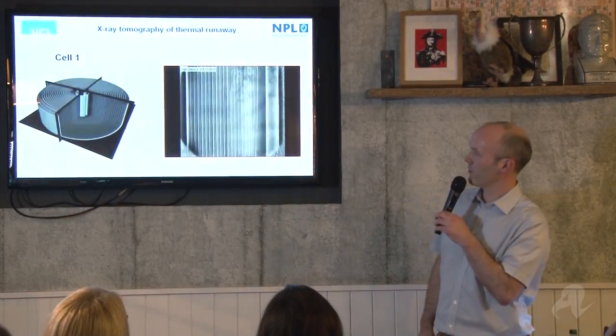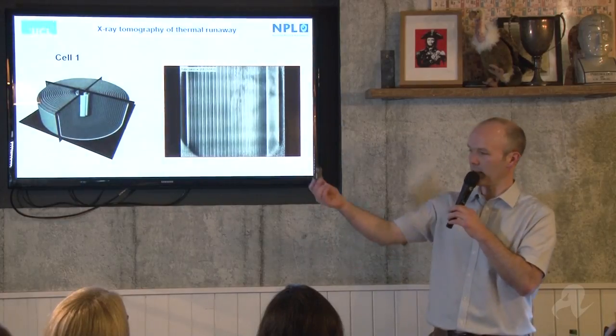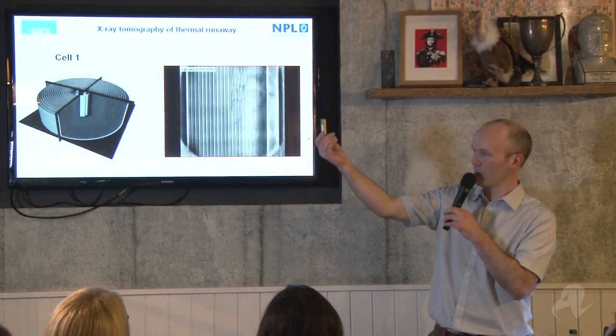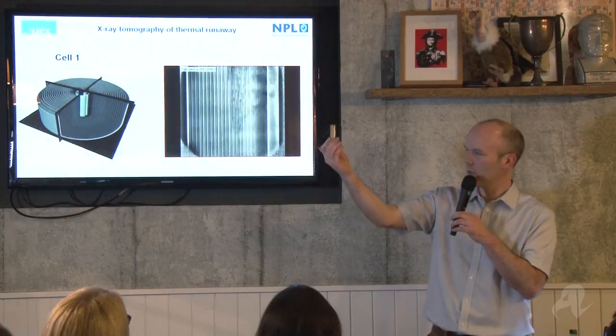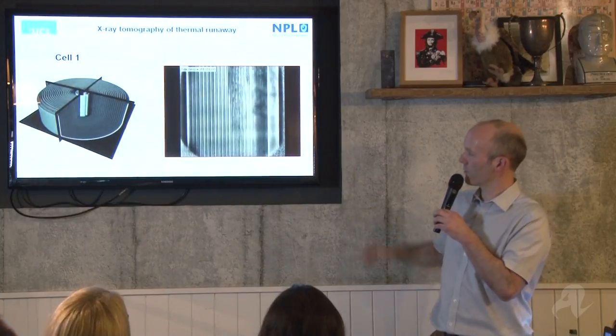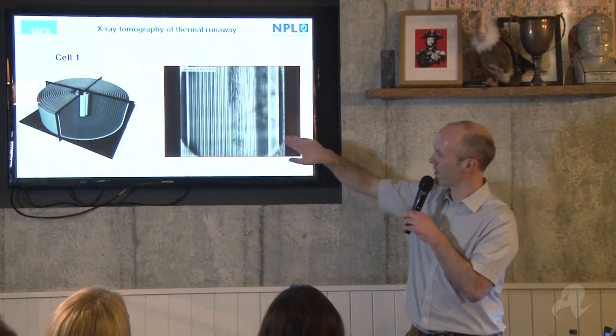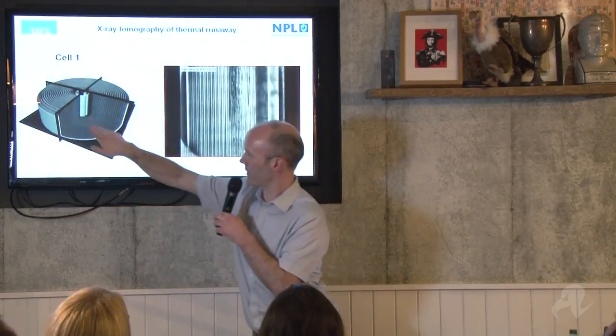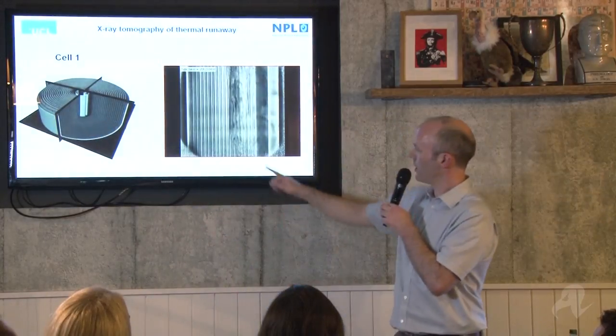So this is an example from cell one. Again, it's just one of these 18650 cells. We were rotating it very fast and firing the X-ray beam through. This is just looking at this part of the cell here. As you can see, the electrolyte in between the electrode sandwich starts to decompose and form gas bubbles. And then the structure of the electrode breaks down.